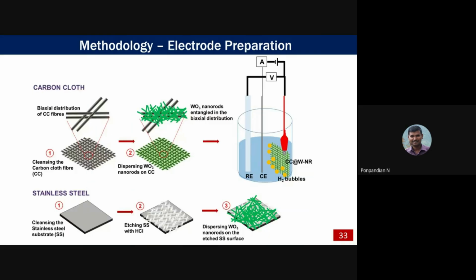And the next, we can deposit this on a carbon cloth that can be used as an electrode. This prepared tungsten oxide material with different morphology can be deposited on a carbon cloth. You know that carbon cloth has better electrical conductivity. In that way we are using that as an electrode, and this material can be coated on that particular electrode for further application. This is what this particular slide explains.